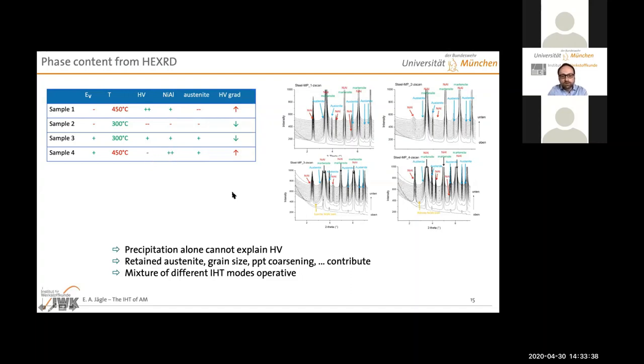Clearly the austenite plays a role. Possibly we have to look at not only precipitation, but precipitate coarsening. We have to look maybe at segregation effects, which again have an interplay with the amount of retained austenite very strongly, and so on and so forth.